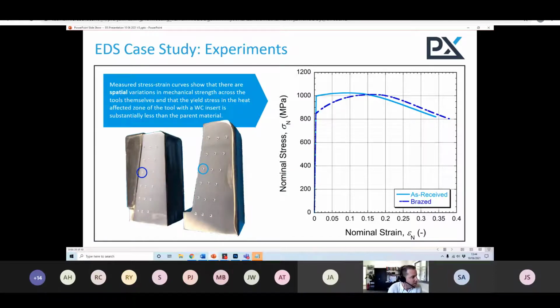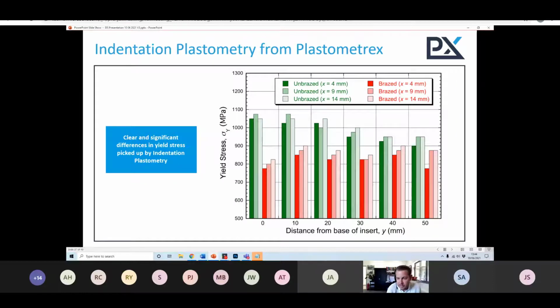Okay. Now, that is just a comparison between two corresponding locations. But it's possible to do the same analysis across the grid of indents, and the red bars in this bar chart are for the brazed sample, and the green ones are for the annealed sample, for the as received sample. And you can see quite clearly that brazing treatment has substantially affected the yield stress in all of the locations that were tested. Okay, so there's essentially been a uniform reduction across the entire specimen, but just to different degrees. So that's really useful information, and once you know spatial variations in mechanical properties like this, you can actually predict spatial variations in wear rates as well, and then get a better handle on what the wear performance and the wear life of these components will really be.